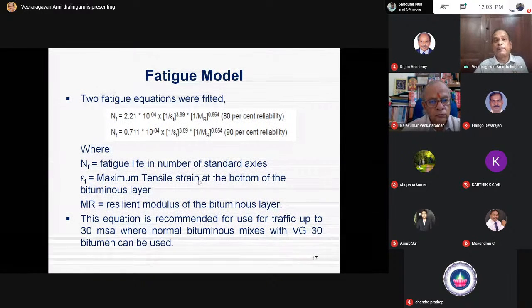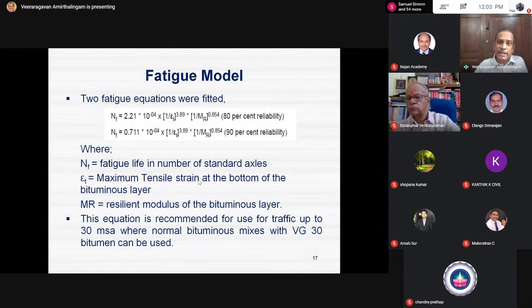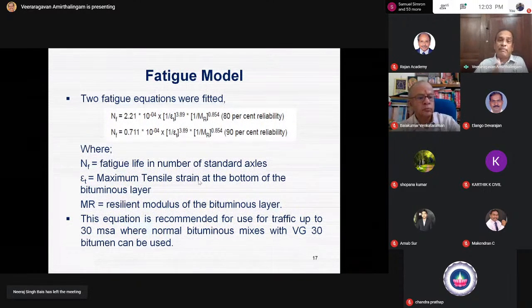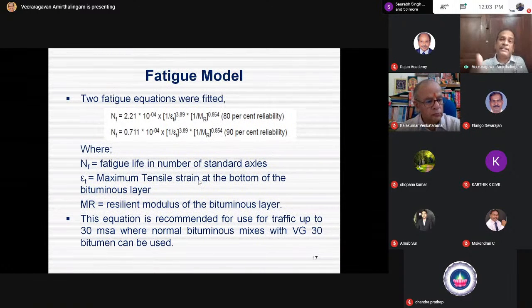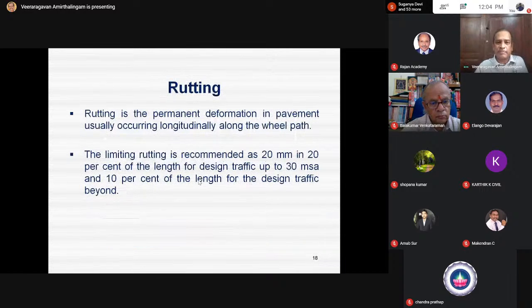This is what I contested at the beginning. These resilient modulus are based on laboratory models. Laboratory midpoint gradation, optimum binder content at exactly 35 degrees, test it and then get a model. But in the field, the pavements are subjected to different loads at different temperatures, different density, different compaction. The performance is different. So this fatigue model may not truly represent the field performance, but still for design purposes, you can have this fatigue model.